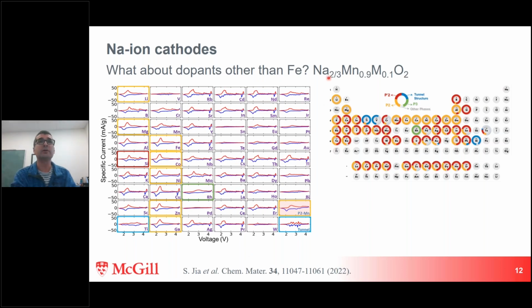So here we took sodium, manganese, oxygen. We took the iron away, and we wanted to see what other substituent could play the same role of iron and potentially improve the air stability. And so in yellow, we find quite a few dopants that really help with the electrochemistry. They do the same role as iron, right? Very smooth curve here. And they ended up making purely this P2 phase. So really good performance.